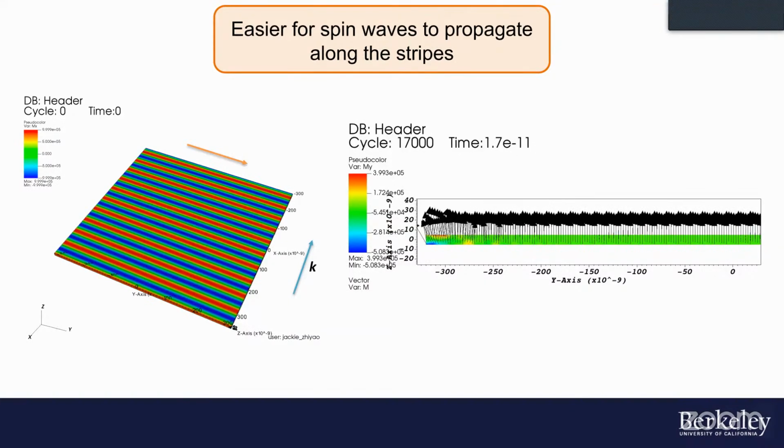In these simulations, we have to impose such a high anisotropy to actually get the ground state that the actual frequencies we get are not anything reasonable. I think the conclusion we've come to with the folks doing the simulation, as well as some folks doing analytical calculations, is that in this direction it looks a lot like a ferromagnet.